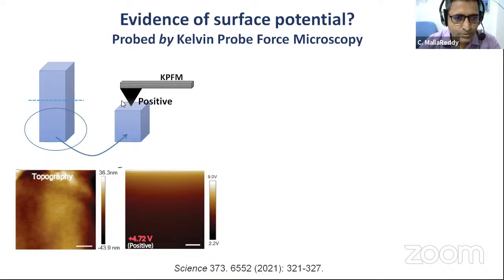So what you are trying to do is to map the electrical potential on the surface. You basically go around, exactly like AFM. It will map it, and then you know how much electrical potential you have on the surface. We see that the average potential is around plus 4.72 volts, which is quite a lot. This is after 15 minutes of the breakage, because we have to make the sample, and this took about 15 minutes. In the first run, this was the maximum that we got, but in other crystals we got less. So it is about plus 4.7 volts.